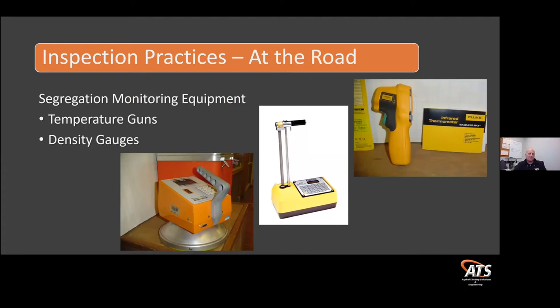Let's talk about some of the tools. Out there on the roadway, the quality control technicians all have density gauges, and it's a great way to indicate whether you're not getting density. If you get a severe drop in density, you might want to start looking around at the paving mat and see if it's segregated. Also, just monitoring the temperature with one of these infrared temperature guns,